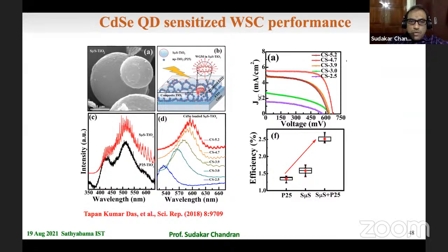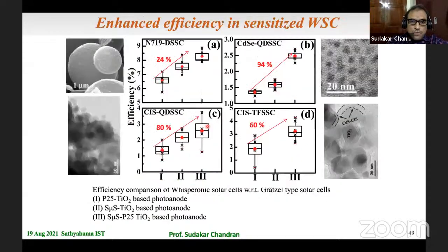So we used cadmium selenide quantum dots, and without the micron size spheres, we get something around 1.6, less than 1.5 percent efficiency, whereas it can go to 2.5% the moment we introduce these whispering gallery mode exhibiting micron size spheres.